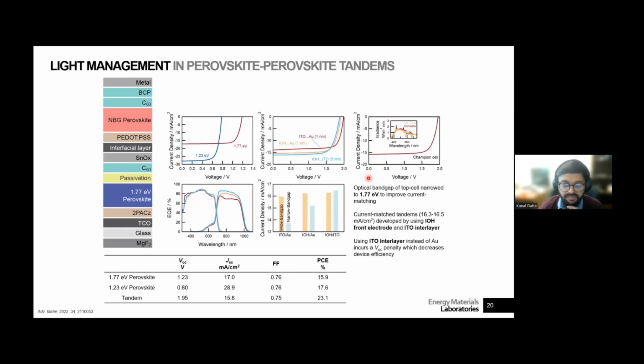So finally, we do that by changing the bandgap of the wide bandgap cell, because there's not much else that you can do. So we narrow it a little bit, going from 1.80 to 1.77 eV. That shifts the bandgap a little bit to the red, and we try to do the same thing again. And this is the IVs of the two single junction cells.